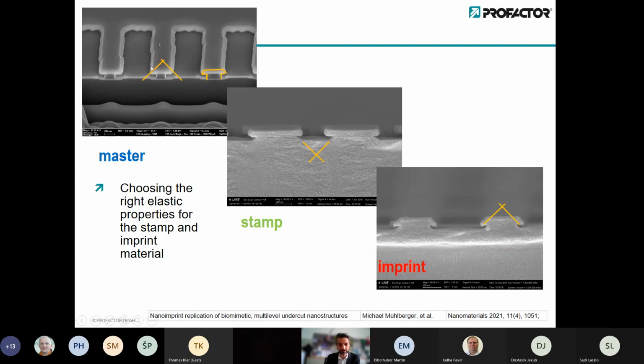So what you see here on the top left is the master, which we used to fabricate the stamp, which you can see in the middle. And the stamp was used to do an imprint, which you see on the right bottom. You can see that from the mastering process, you have a slight tapering angle here, and this is nicely replicated also in the stamp, and finally also in the imprint.